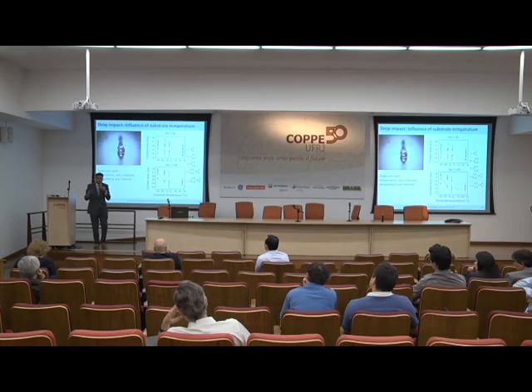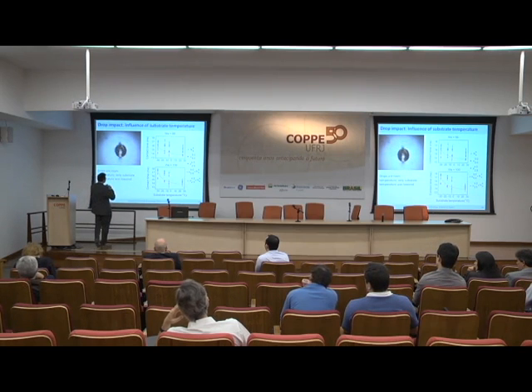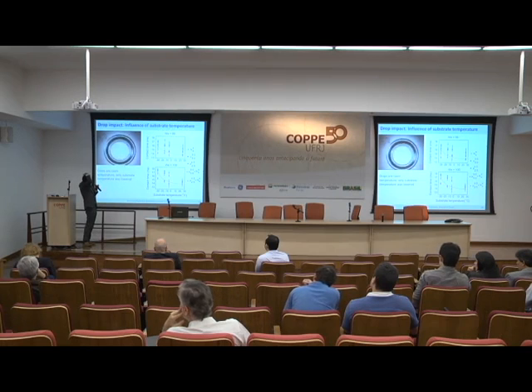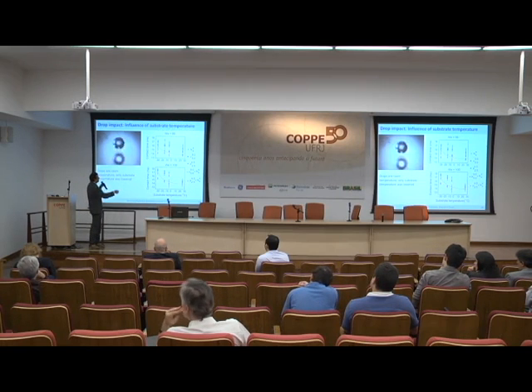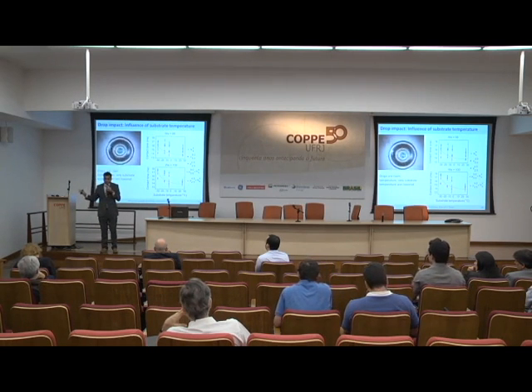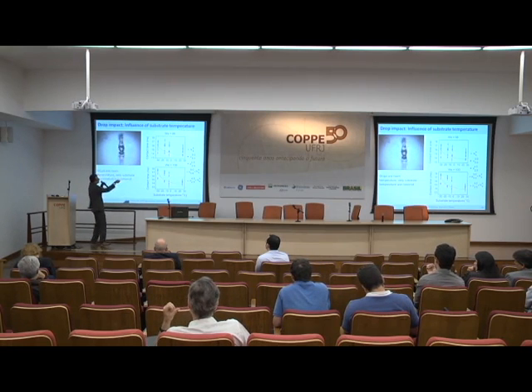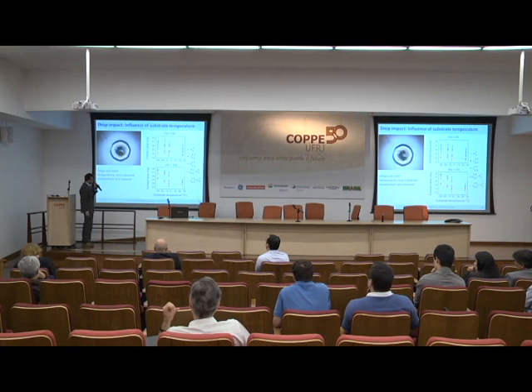This is to be expected, because if I go down in temperature, my viscosity is increasing, right? So if the viscosity is increasing, the viscous dissipation is higher, so the droplet is bound to spend more time. No big deal, okay? And others have seen and proved this. What was interesting, at least to me, is these two numbers here. This is Weber number. Weber number is basically the ratio of inertia to surface tension. That's the simplest way to think about it. So we're looking at a velocity here, let's say, of maybe less than a meter per second, and we're looking at a velocity of 2 meters per second.